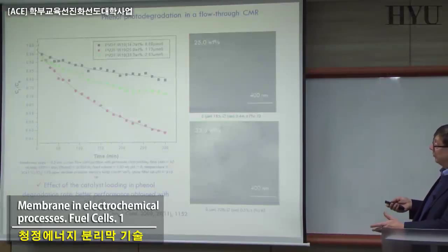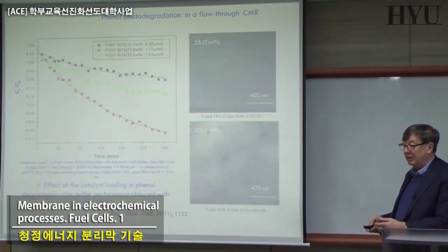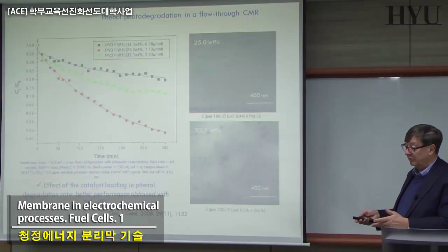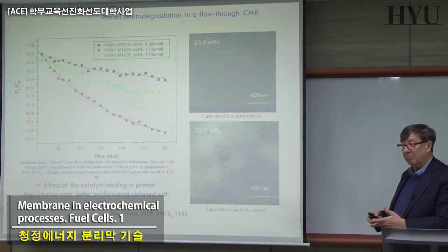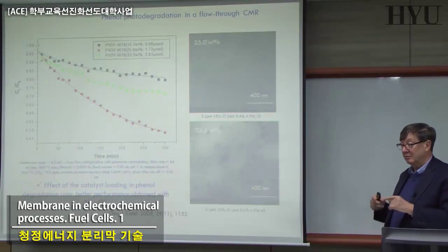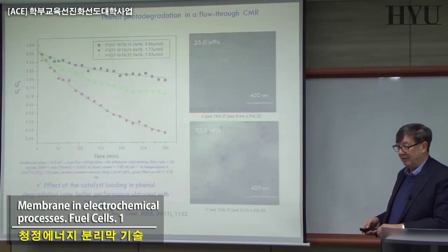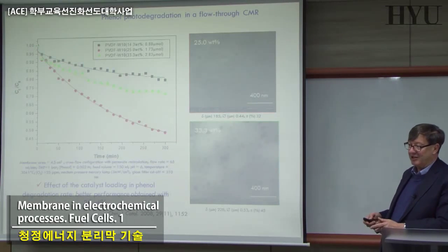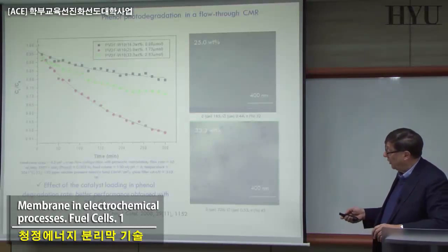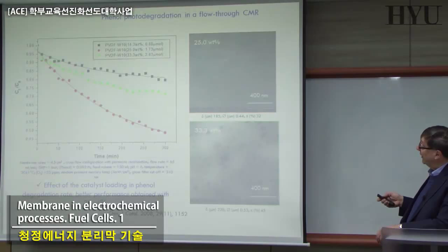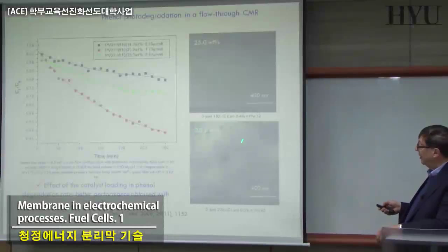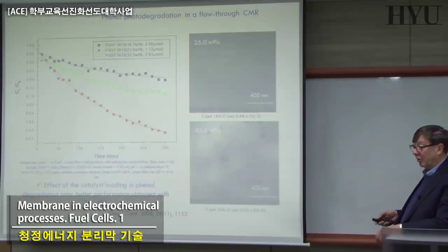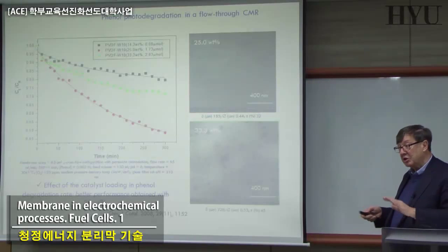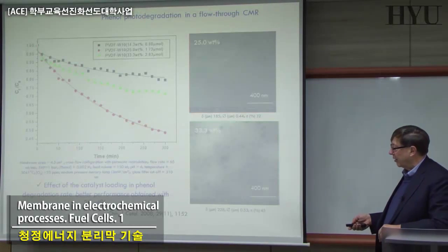You can have an effect where you are producing a kind of composite material, and depending on the size of your particles and the kind of system you have at the end, you can have a better improvement, in elongation and tensile strength. In other cases you are inducing some weakness in the mechanical properties, some fragility, and you break the system. So this is one of the areas that you have to analyze carefully, and you see here that you have to check at 25%, at 33%, eventually with the same level of thickness, in such a way that you know which parameter is really affecting the final result.